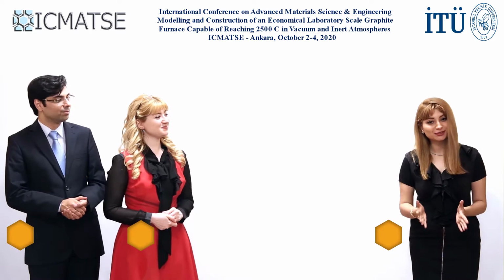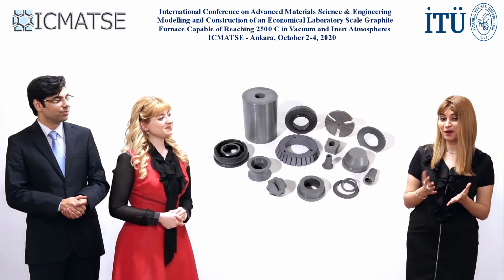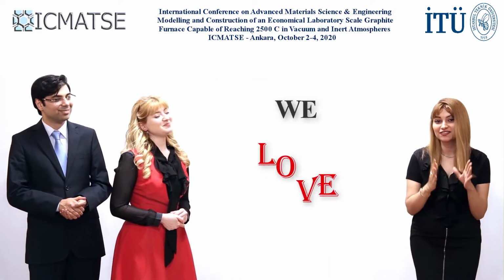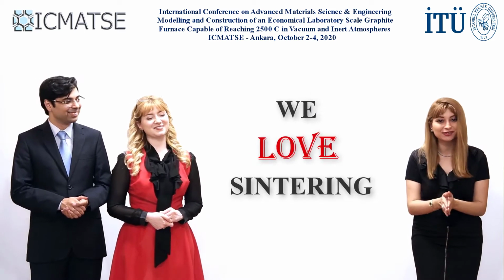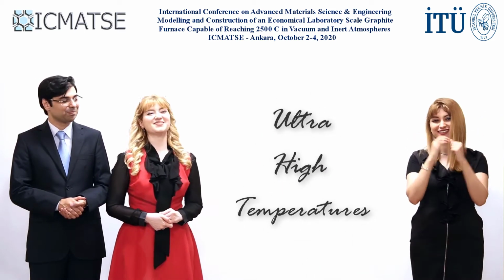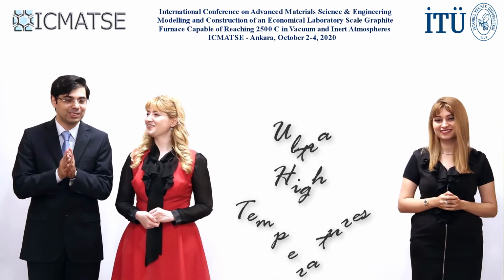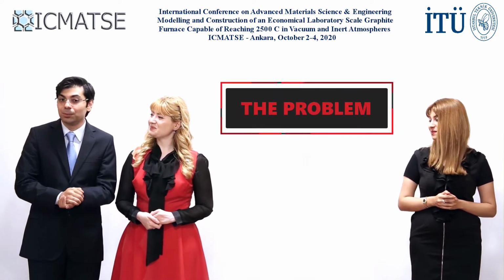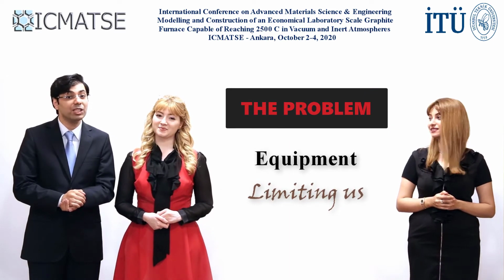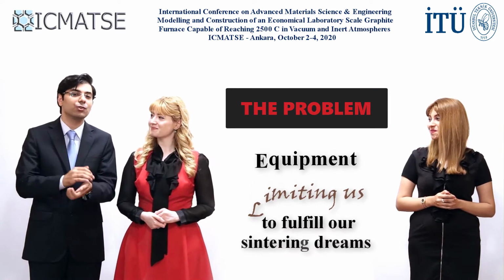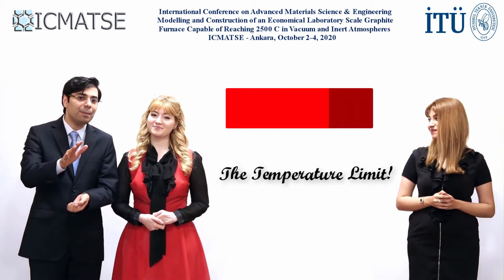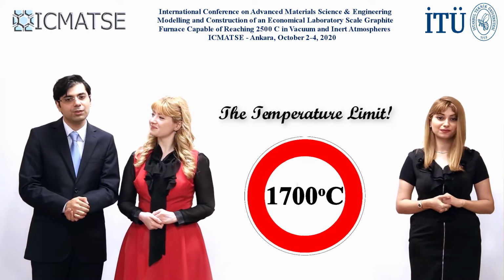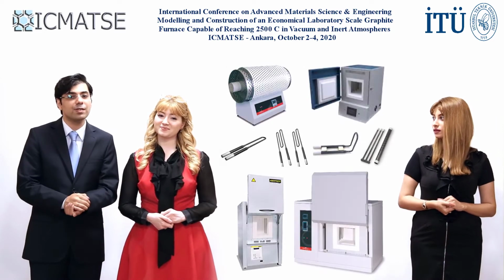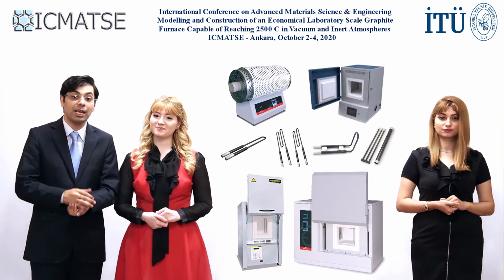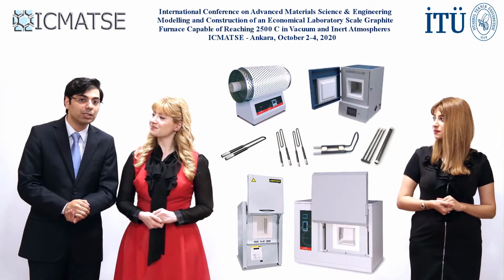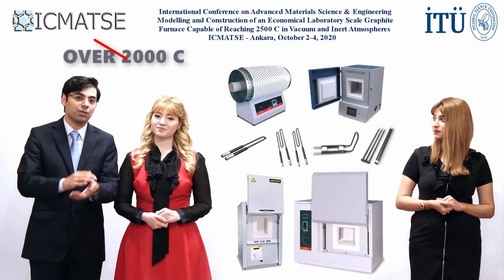Just like any other researcher in the field of technical ceramics and powder metallurgy, we love sintering, and so the temptation for climbing to ultra-high temperatures is just in our blood. Ever since we started our sintering experiments, there was a single problem which kept limiting us in terms of the capacity to fulfill our sintering dreams. And that was the temperature limit of approximately 1700 degrees Celsius due to the type of furnaces usually available in most labs. And it was not having the right equipment for reaching temperatures over 2000 Celsius.